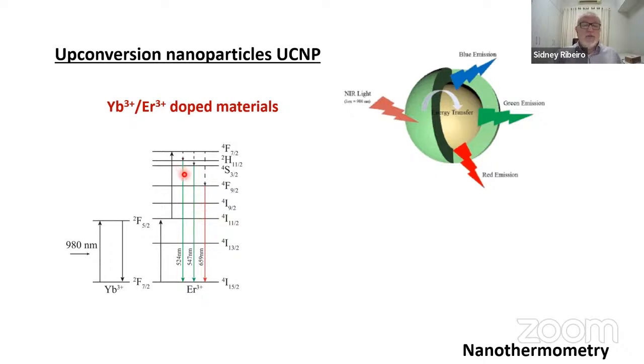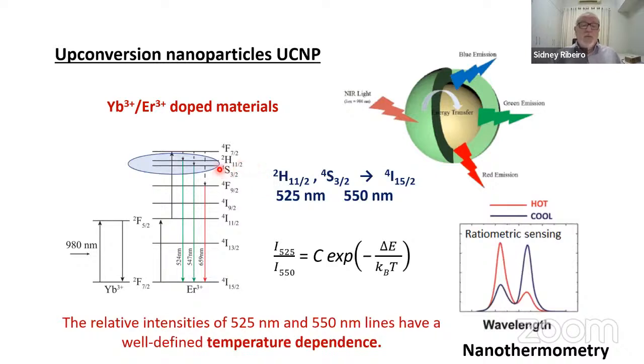In the green, you have two transitions from two levels to close levels. So this is very interesting because the population of these levels, therefore the intensity of these two green lines, depends on the temperature. So the relative population of these two levels obeys a Boltzmann expression like this one. So by playing with the relative intensities of these two green lines, you can have information about temperature. This is a kind of optical sensor for temperature. So this is a very hot subject today, and this is called nanothermometry. So you can use particles to measure temperature, and these are nanoparticles, so you can have temperature measurements in the nanometric scale.